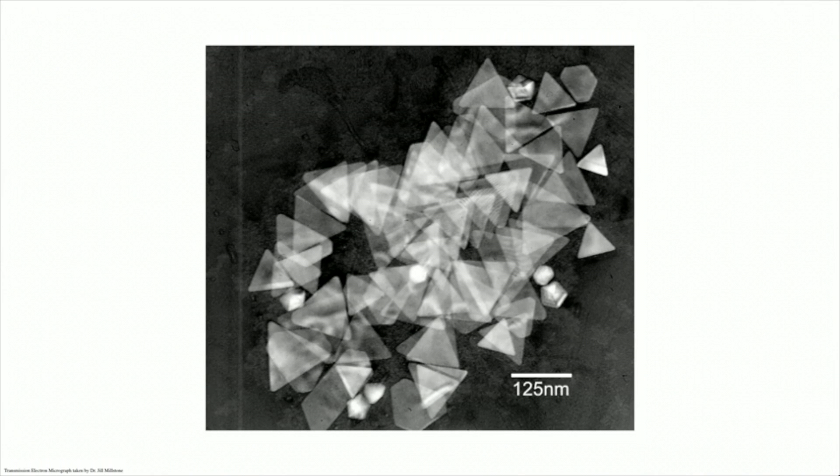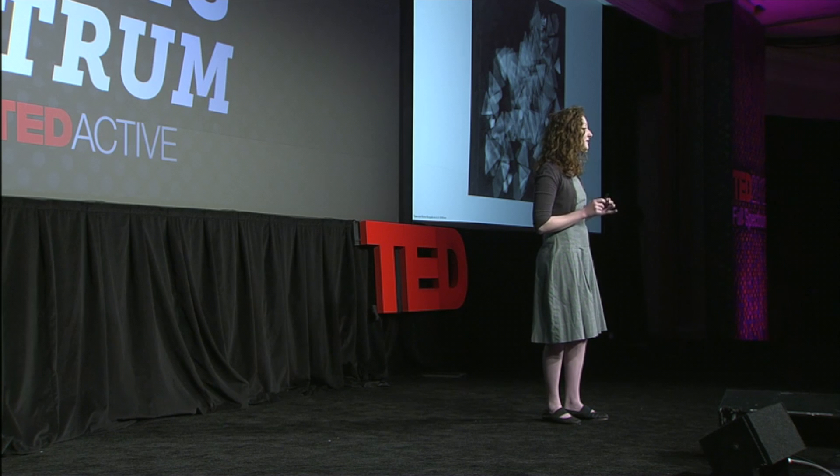The morpho inspired me to seek out other forms of structural color, specifically structural color caused by nanoparticles. It's nearly impossible to imagine how small these particles are — smaller than bacteria, than cells in our body, even smaller than wavelengths of visible light. This is key, because when things become nearly as small as wavelengths themselves, their color is determined by their shape and size.